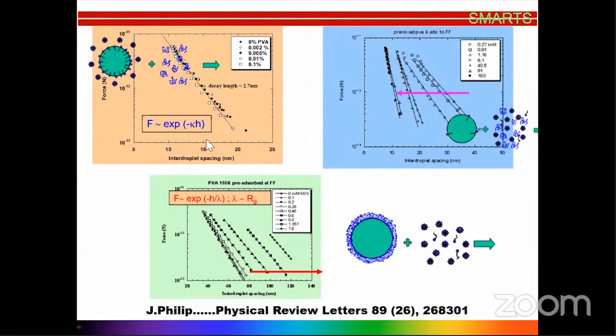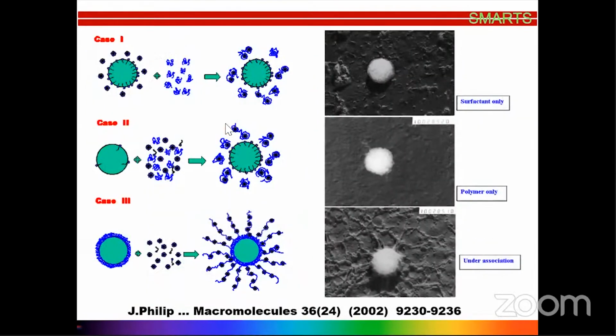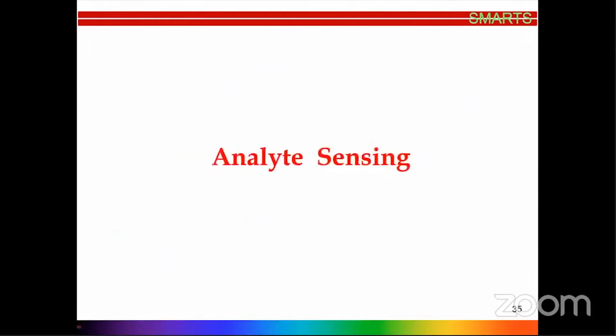That's what we have shown here. The kind of interaction that leads to different kinds of structures and interaction forces. And we could match our experimental finding with the cryo-TEM experiment. That's what you see in this case. The polymer surfactant interaction can lead to huge enhancement in stability of colloid. That's what is demonstrated in this paper.